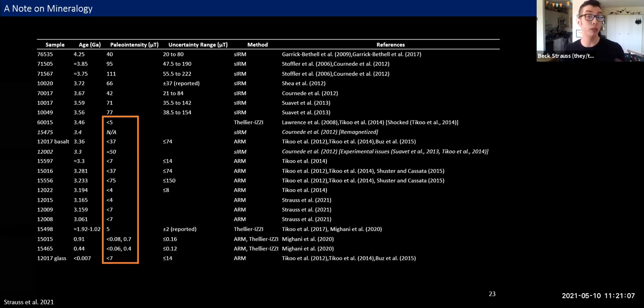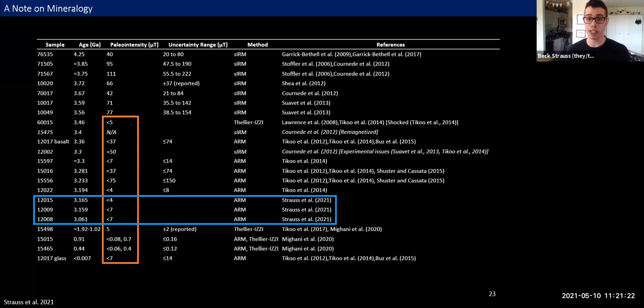You'll notice that there's quite a range of paleointensity fidelity limits reported here. Some samples could record fields weaker than 1 microtesla, while others could only record fields upwards of about 75 microteslas. I was really interested in this variation, particularly because our 3 samples exhibited extremely good, but not the best, magnetic recording properties. So we can use these 3 samples as kind of a case study to help us talk about the magnetic mineralogy of lunar rocks and how they might be recording these fields, or in our case, not recording them.